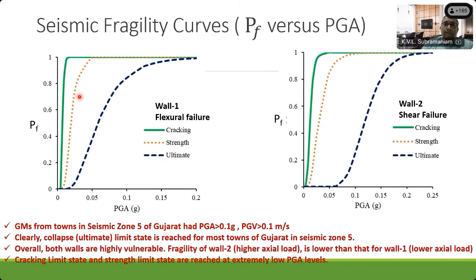So from here, then we can construct the seismic fragility curves for the three limit states, the cracking, strength, and the ultimate, as a function of PGA. And what we find is for wall 1, which is a wall that failed in flexure. That means this is a wall which has an aspect ratio which is greater than 1 and is subjected to moderate level of compression. Here, what you see is that if you go to a very small value of PGA, basically you essentially have a probability of failure hitting 1, which means that most of the walls would be cracked even for a very small jolt that you would get at a very small PGA value.